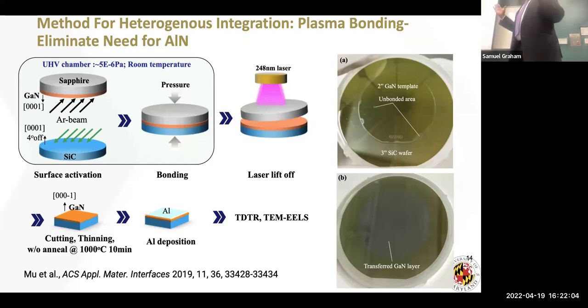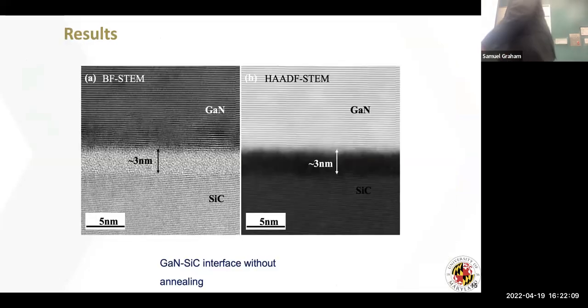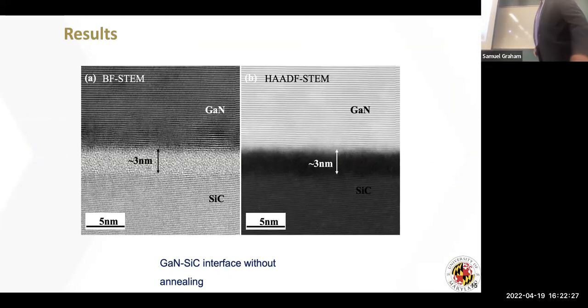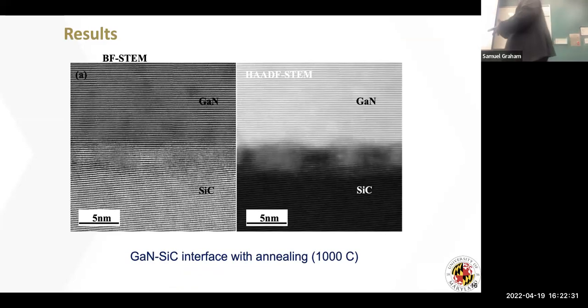So from the cartoon, you would think I would have gallium nitride and silicon carbide placed together, and that's not what happens. Even though I put nothing in there, the bombardment of the ions makes this surface amorphous. So I still have an interface. I tried to get rid of that amorphous interface, something in the middle. And so what we can do is go back and try to anneal it. If I go through an annealing step after I do the bond, you can see that it kind of recrystallizes. You can see the planes here. You see some fuzziness here.